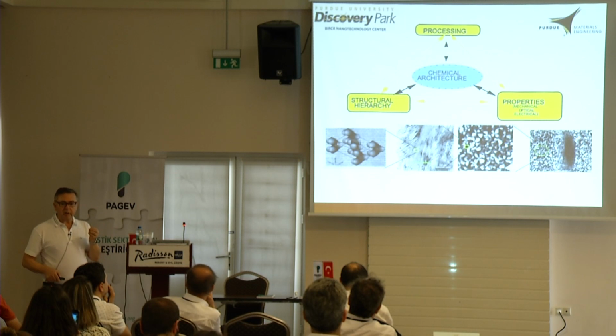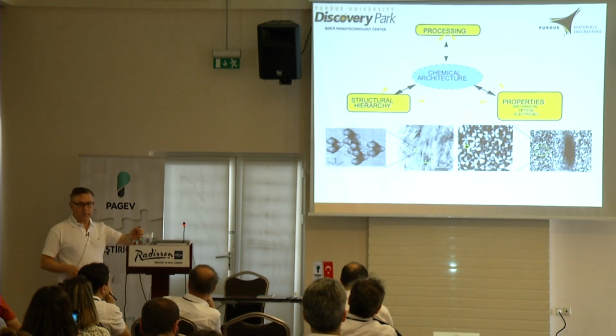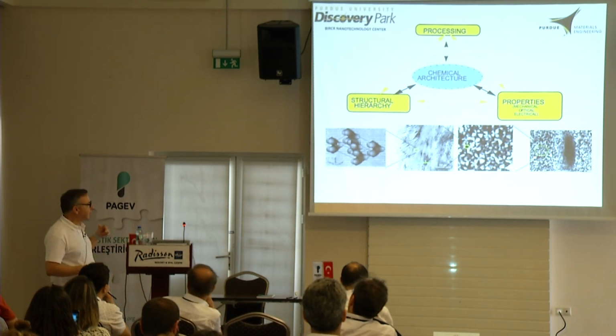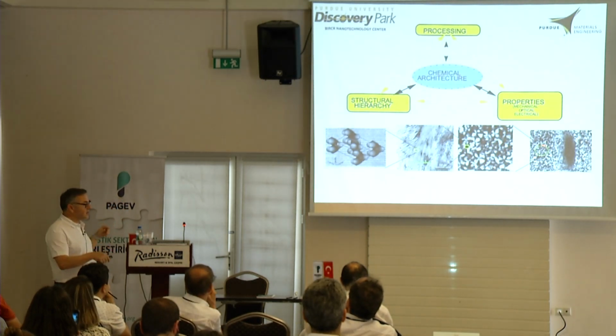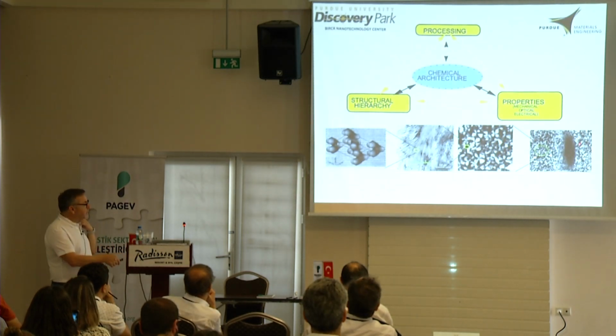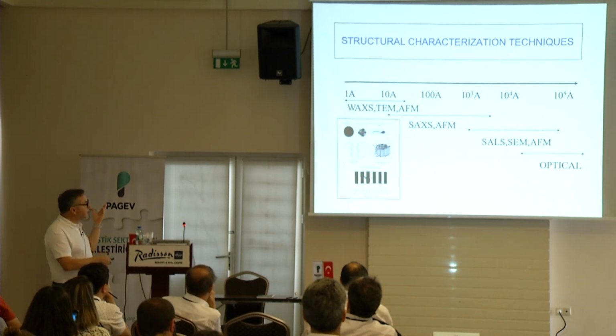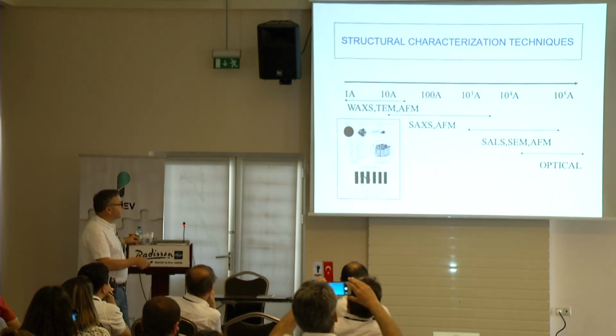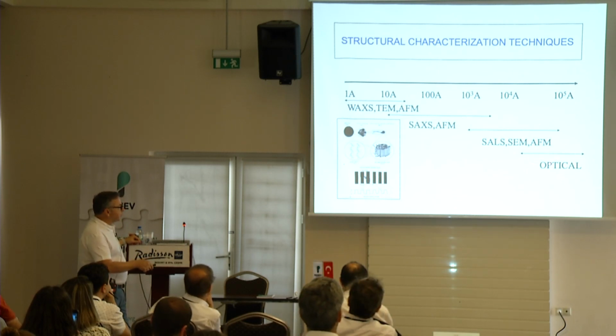And then if you truly want to understand how the process conditions, the injection speed, the mold temperature, the temperature of the melt influence the other properties, you really need to be able to characterize at these length scales. You can certainly start with the optical microscope, but by the time you get here, this is a transmission electron microscope. And if you want to go to this level, you need to do X-rays. So we use a range of techniques. Optical gives us reasonably large size information.